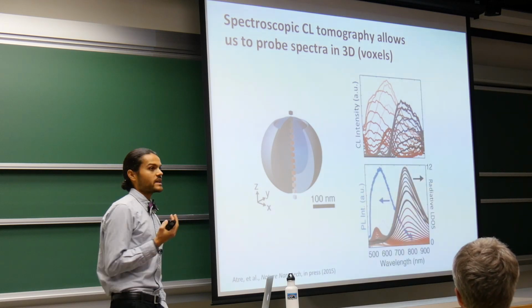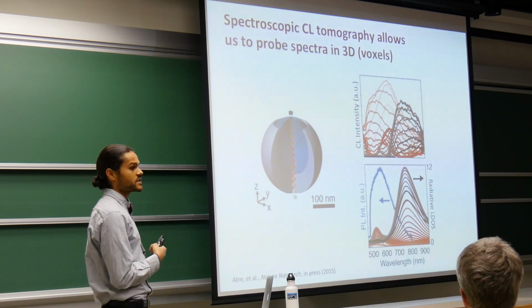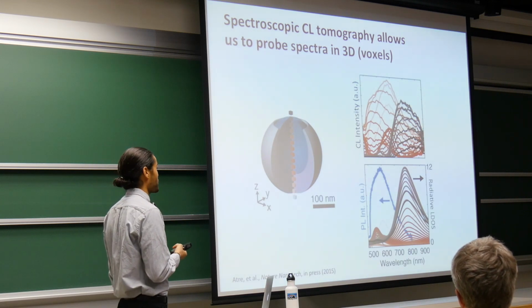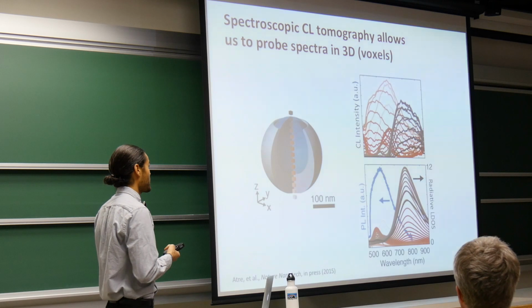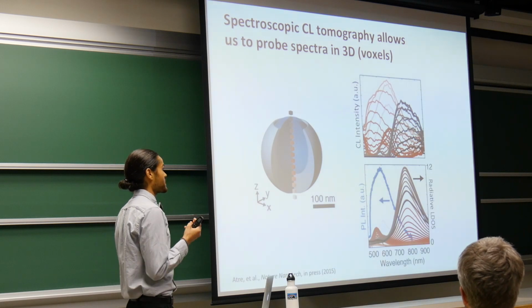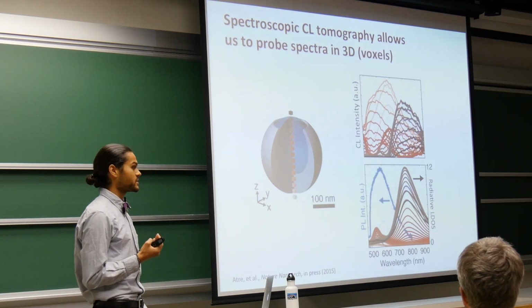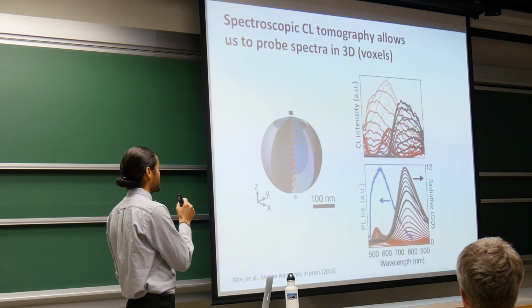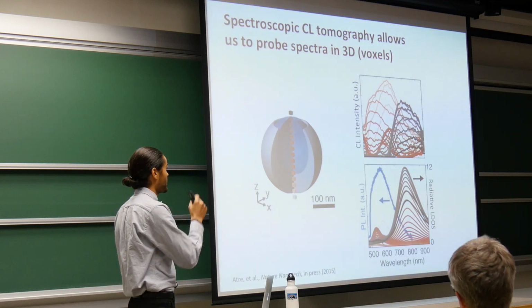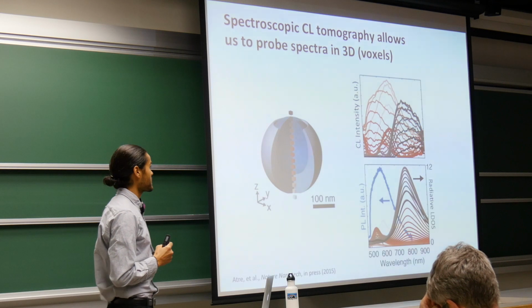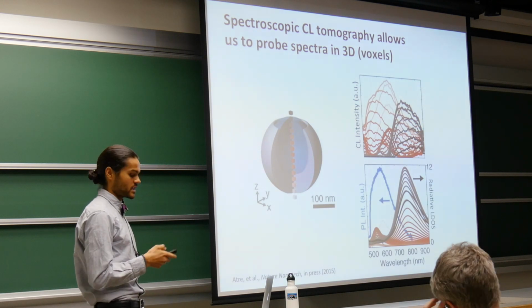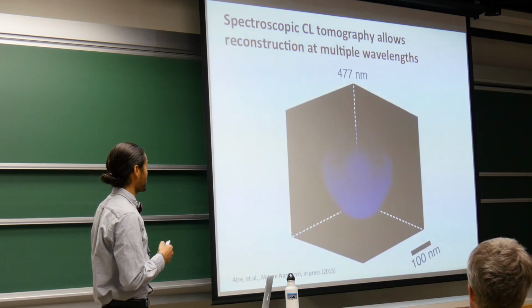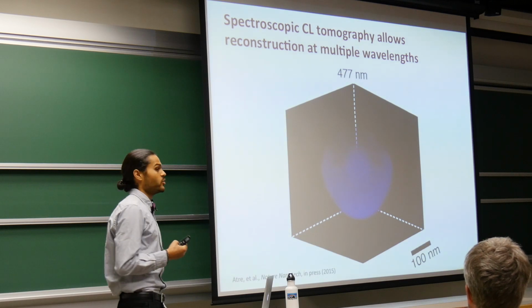We can actually correlate that to real physical quantities. As I've mentioned before, the material luminescence can be probed through photoluminescence measurements, but more interestingly, we can actually calculate the radiative local density of optical states in these particular nanoscale voxels, and they actually correlate quite well with the signal that we get in our 3-dimensional tomograms.